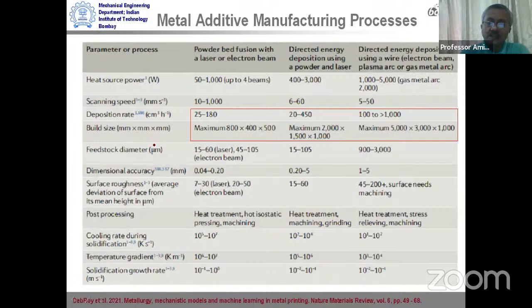If we look at the build size, powder bed fusion with a laser or electron beam builds, so far, based on the available information in the literature, a typical maximum of 800 by 400 by 500 millimeters. In contrast, we have nearly 2 meter by 1.5 meter by 1 meter size of deposit or final part by a DED process with a laser, typically LENS, as some of us, I'm sure, are aware. And in the gas metal arc based process, we see that the build can go up to a much higher size, like 5 meter by 3 meter by 1 meter, for example.